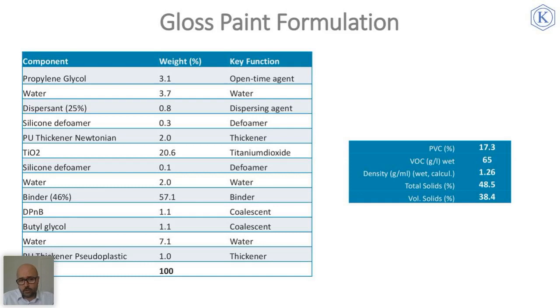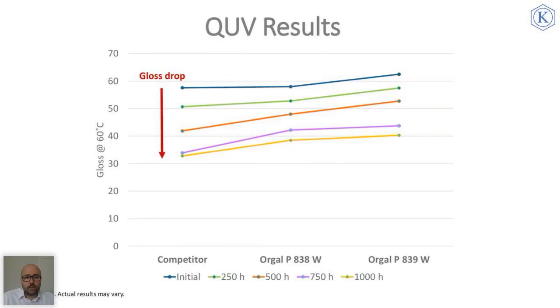Another paint formulation, gloss paint formulation, was used in QUV in order to better assess the gloss drop of the paints. In this graph, we are seeing the gloss measurements at 60-degree angle with initial gloss after 250 hours, 500 hours, 750 hours, and 1,000 hours.